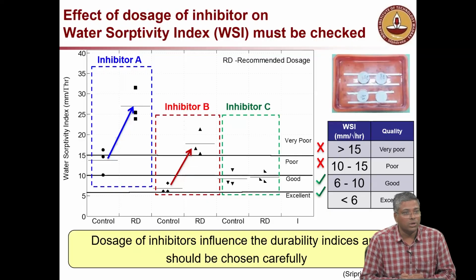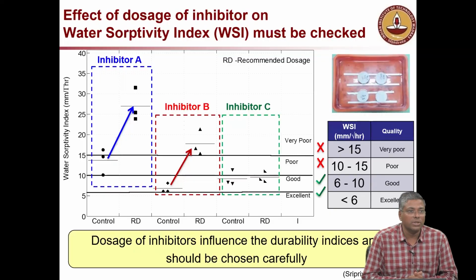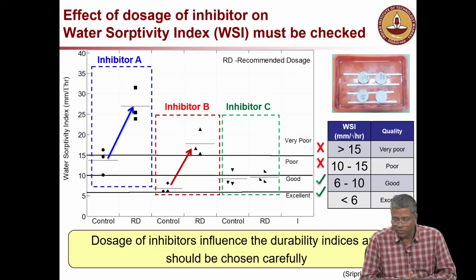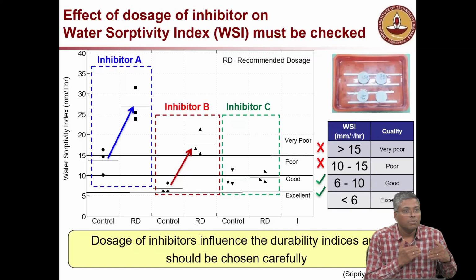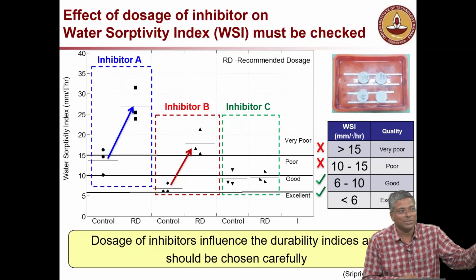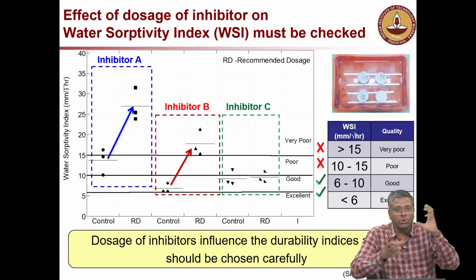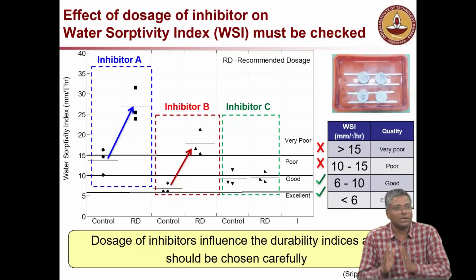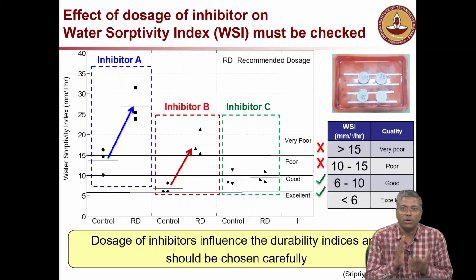One is control, a recommended dosage. You can see that once you put the inhibitor, the sorptivity is going from, in the blue case, what is happening? Sorptivity is going from what category to what category? Look at the table on the right side. From poor to very poor. It's changing. So inhibitor is good or bad? Bad. Second case, also it is changing from a better category to a worse category. But these two inhibitors actually showed better corrosion resistance. So we have to look at both the aspects, what it does to the steel and what it does to the concrete. Anything you mix in concrete, you have to look at both the aspects.